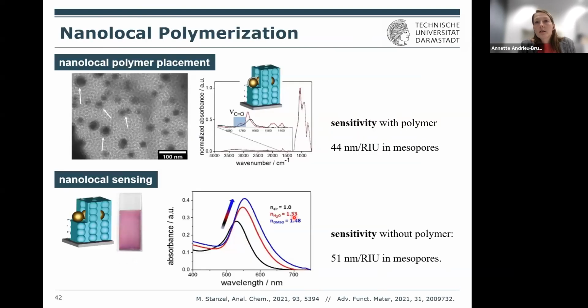I skipped the other data. And I wanted to show a last slide with the infrared spectra. This is maybe the most important, where you see that if you do just the far field irradiation at the suitable intensity, there's no polymer formation. But if then you have the particles present, due to the field enhancement, there is polymer formation.